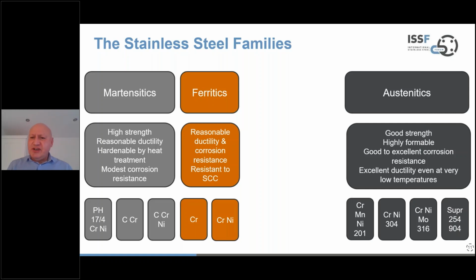And then also we have the austenitic group, which many people are familiar with, the 18-8, the 18-10 stainless, and the more highly alloyed group, with good strength, very formable, good to excellent corrosion resistance, and no ductile to brittle transition. So this is a very useful family of stainless steels. These are typically the chromium nickel steels or the chromium manganese nickel steels, and even some higher alloy variants.